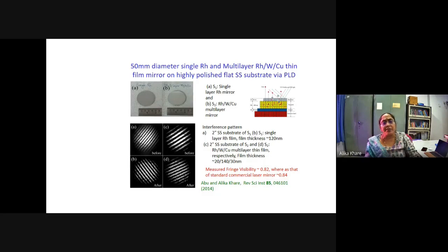So one of the mirrors of the interferometer was replaced by these mirrors, and one can see the parallel fringes. The perfect parallel fringes clearly demonstrate the quality of the surface of the film, because the reflectivity also gets affected if the surface quality is very poor. So here the perfect fringes clearly demonstrate that the quality was very good.